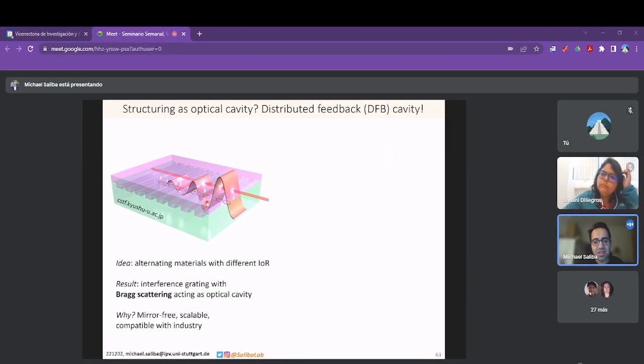And those require at least the laser optical cavities. So a famous optical cavity is, of course, the Fabry-Perot, where you have mirrors at a certain distance. Another one, also extremely well known, is to use alternating different indices of refraction in order to induce a standing wave. And that means backscattering. And that means the optical cavity is written into the material by structuring it. And why is that used? Because it's mirror-free, scalable, and compatible with industry. So distributed feedback or distributed Bragg reflectors, very well known for lasers as well.